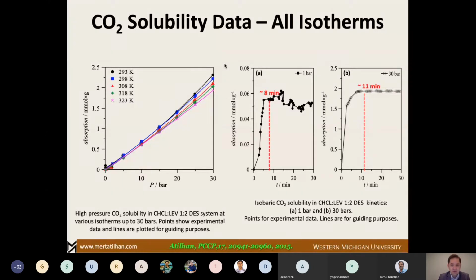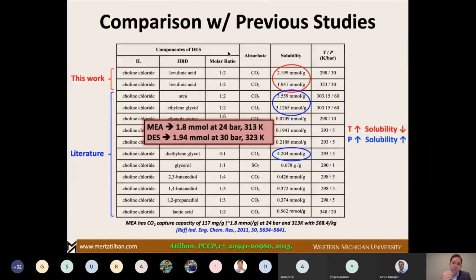So we started to look at the kinetics. The kinetics was not so quick, but not so slow. Especially at the lower pressure side, we were talking about reaching equilibrium within 8 minutes. And as we increase the pressure, we have seen around 10, 11 minutes to reach equilibrium of the CO2 solubility.